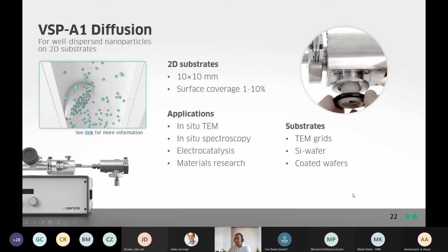The requirements are that these substrates are flat or two-dimensional, and they can have a maximum size of 1 by 1 centimeter. And by varying the deposition time, we can vary the surface coverage of these substrates between 1 to 10%. Applications in which we see this accessory being relevant include in situ TEM, in situ spectroscopy, electrocatalysis, but also just general materials research. And common substrates that have been used are TEM grids, silicon wafers, and coated wafers.